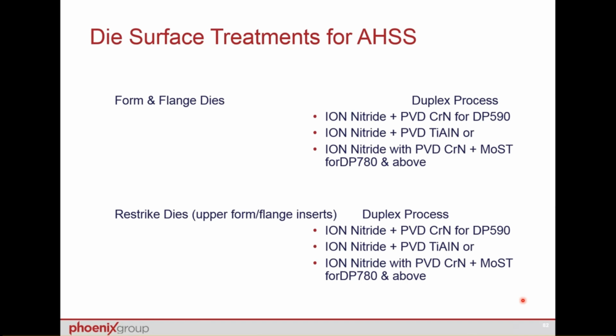Advanced high strength steels, and this is basically recommendations from the World Auto Steels and Auto Steel Partnership. They're talking about for forming and flanging dies. Typically, for materials that are up to 590 megapascals, you're going to want to have an ion nitrided base with some sort of a physical vapor deposited chromium nitride coating. You could be ion nitrided with titanium aluminium nitride or some other type of material. For materials of 780 or higher, they're talking about ion nitriding with chromium nitride plus. I believe the MOST is a particular trade name of a process for coating.